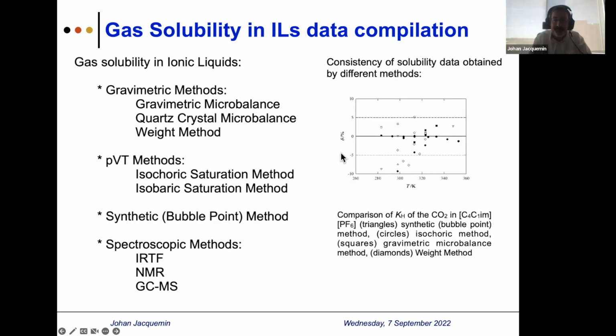Just to give you an idea, this is C4-MIM PF6, butylmethylimidazolium hexafluorophosphate, a very well known, stable ionic liquid. By looking at the CO2 data published at 1 bar, one can see that the deviation is around 5%. A 5% deviation for gas solubility is huge, and specifically for CO2. If we analyze the same with oxygen, hydrogen, argon, nitrogen, we could be up to 200% or more within the literature data. This is a big problem.